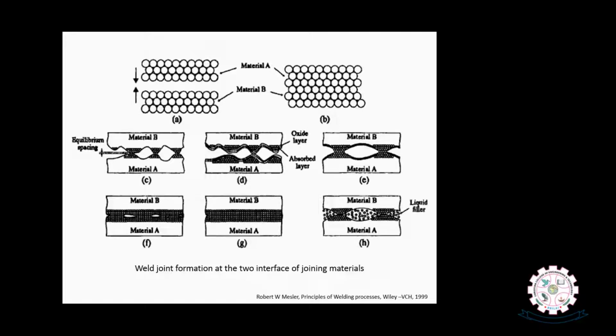But practically, even for mirror-finished polished surfaces, we find the presence of numerous valleys and peaks, as well as oxide layers. Therefore, either we have to apply a higher amount of load by applying pressure, so we can suppress these valleys and peaks, or we can add additional atoms of material A or material B belonging to both surfaces in the form of molten metal, by melting a filler material or by melting the base material itself. So in welding, we apply pressure, or sometimes heat, or sometimes both together.